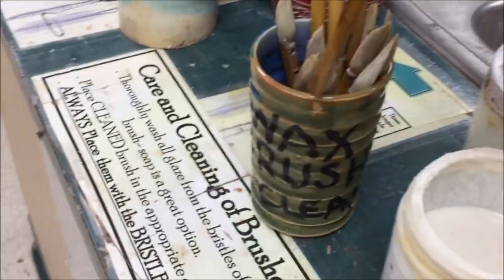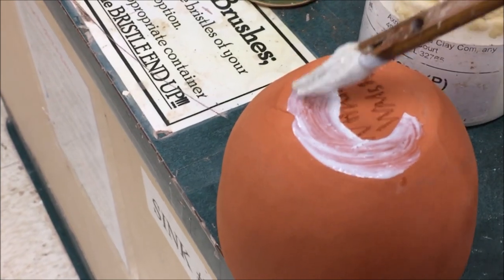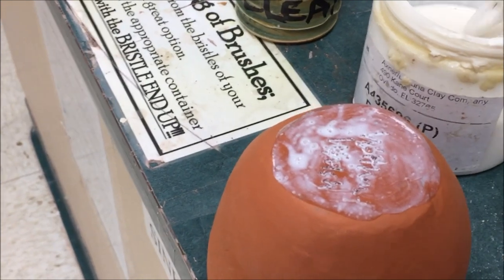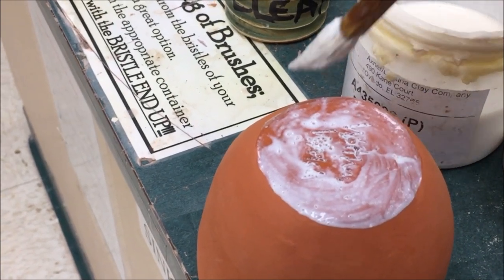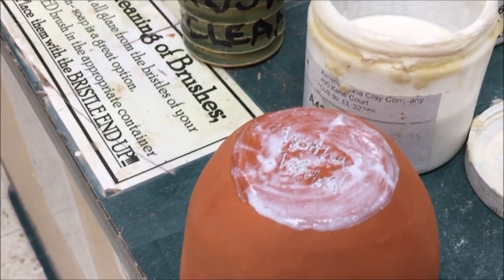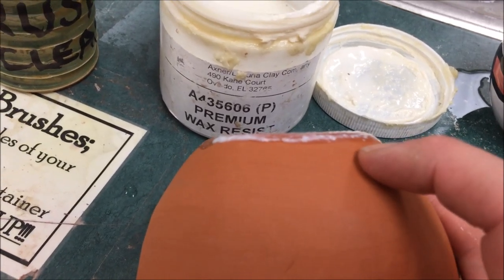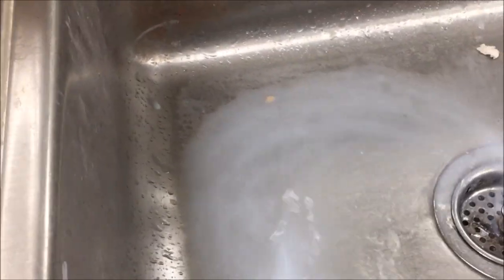Make sure your hands are clean when you do this and grab a clean wax brush — don't use a regular glaze brush. We're going to put one coat of wax on it, being very careful with the wax application, because if you're messy with it, it will resist the glaze. Wherever you get wax, the glaze will not stick very well. You want to go up the edge ever so slightly, about an eighth of an inch. When it dries it will look a little more clear, and you can see I've gone up about an eighth of an inch with the wax.